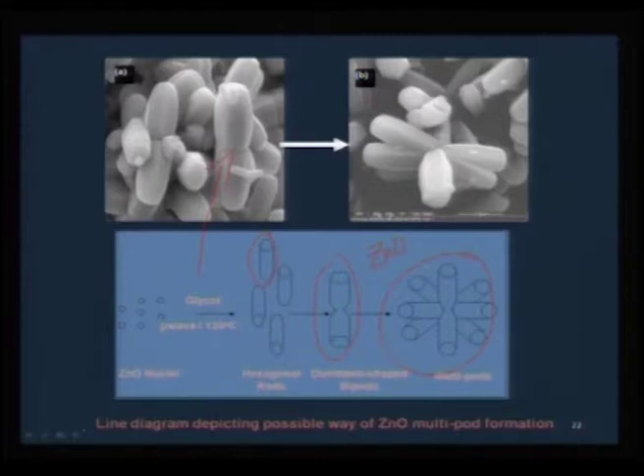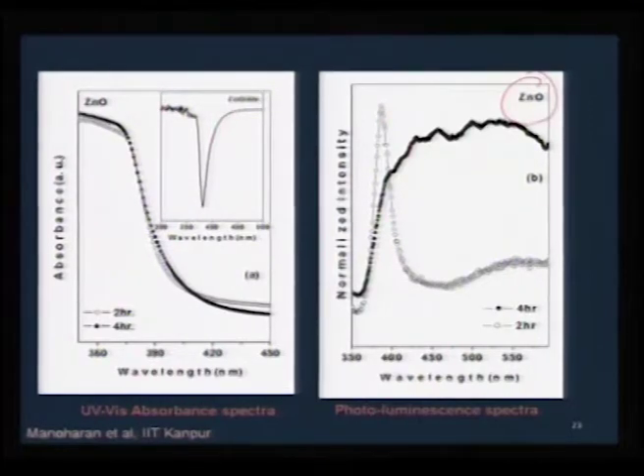And not only making these materials with preferred orientation and morphology, you can also see from here this same zinc oxide, when it is actually prepared using sonochemistry, exposing this to microwave for 2 hours or for 4 hours can explicitly change the PL properties of this zinc oxide. As you would see here, 2-hour microwave exposed zinc oxide can show this 380 nanometer band to band emission, whereas if you expose it for 4 hours, then you see that a lot of defect induced PL is seen. So you can very clearly see that not only do we try to make an approach which is suitable for a particular morphology, we can also fine tune the physical properties based on the structure and morphology of these materials. So microwave certainly plays a very important role in today's materials chemistry approach.